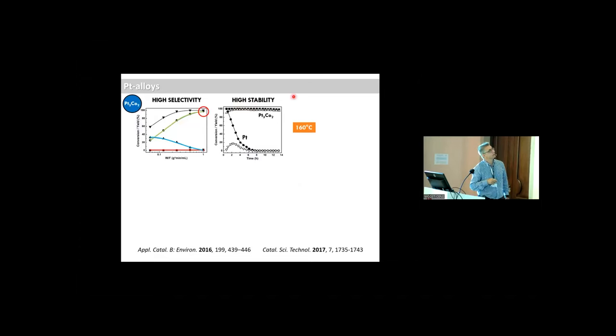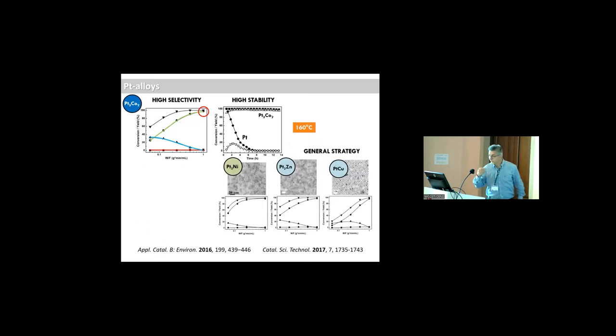Stability is high, you can see, much higher than single platinum. I mentioned cobalt has ethical issues, but after that, we replaced cobalt by nickel, which may have some toxicity problems, zinc or copper. And in all cases, you have a high selectivity and high yield.